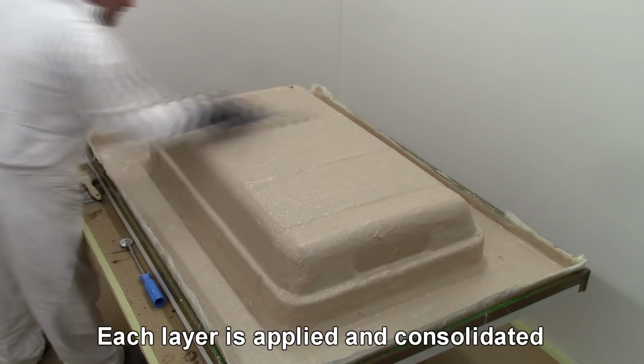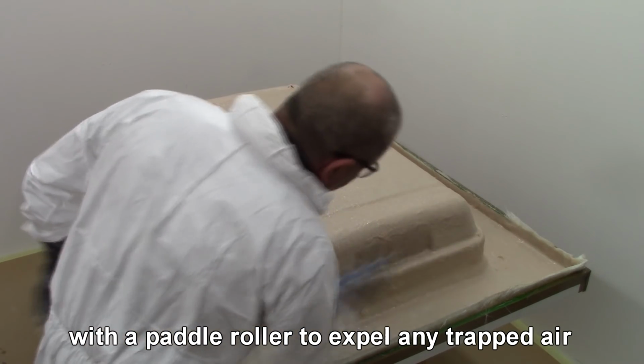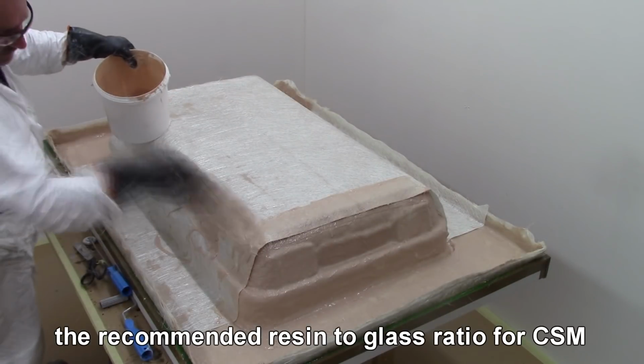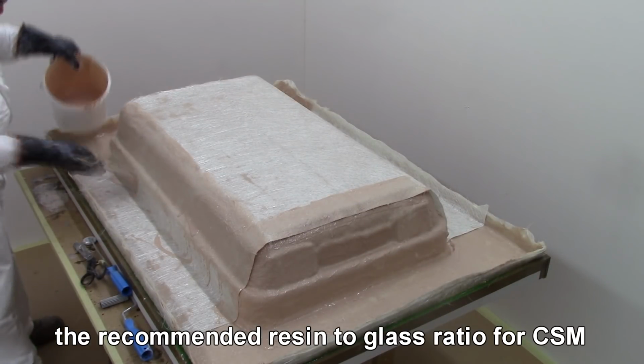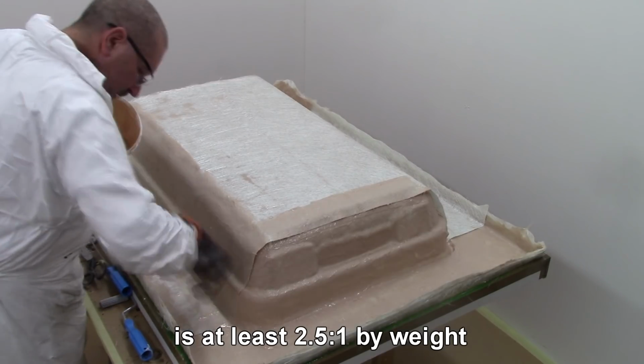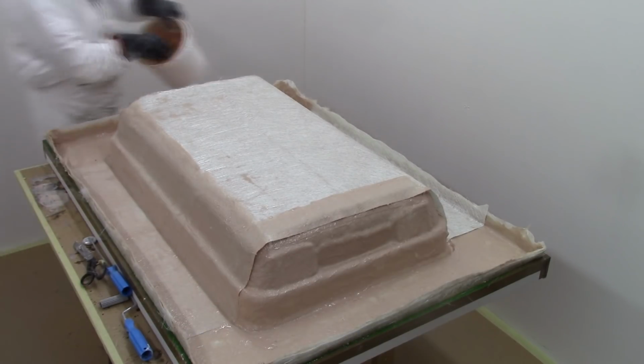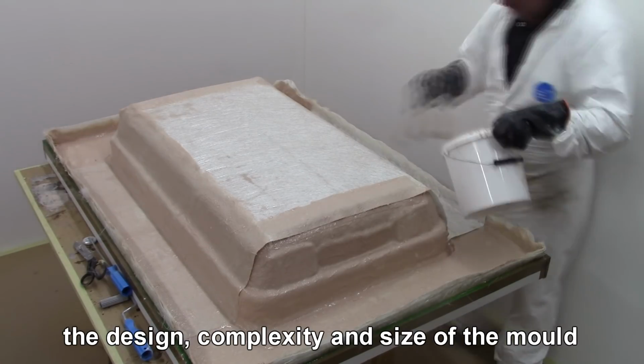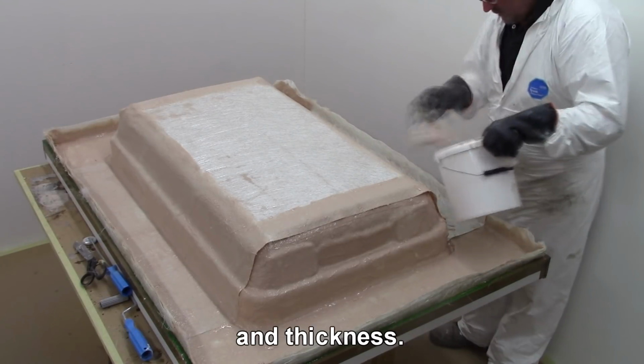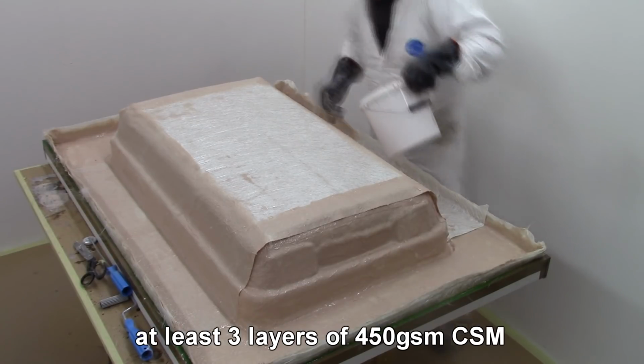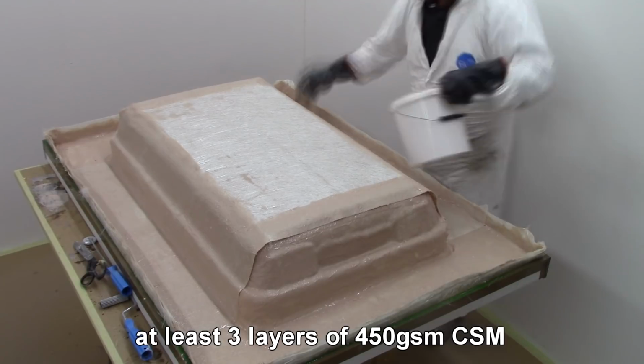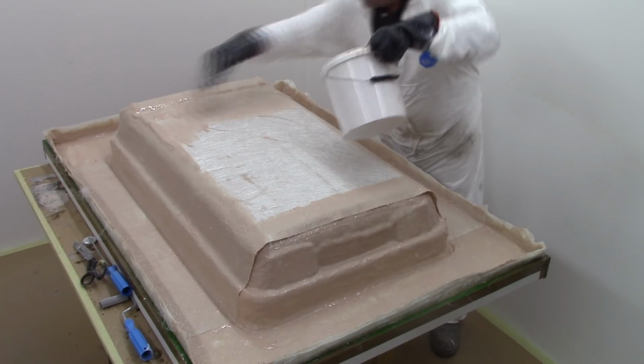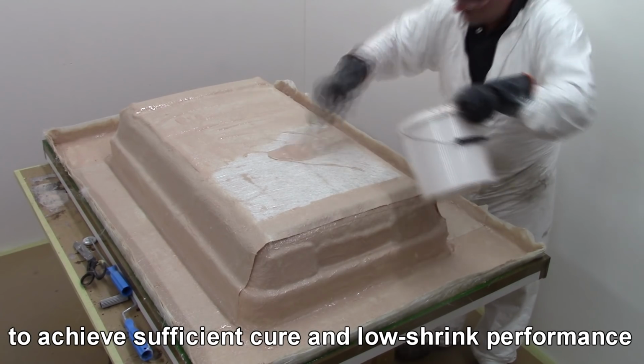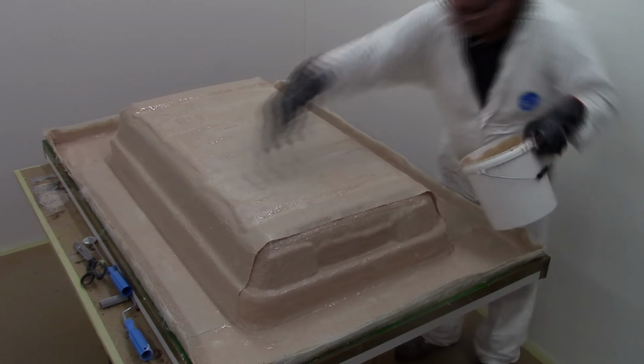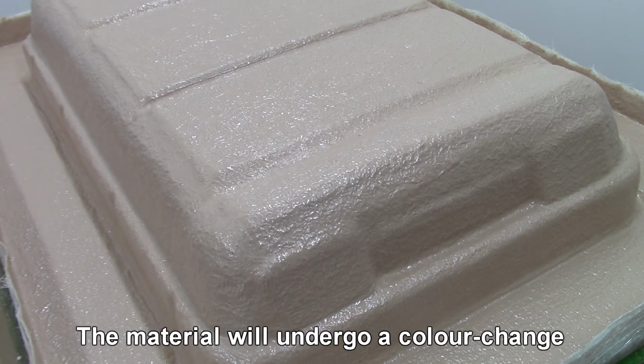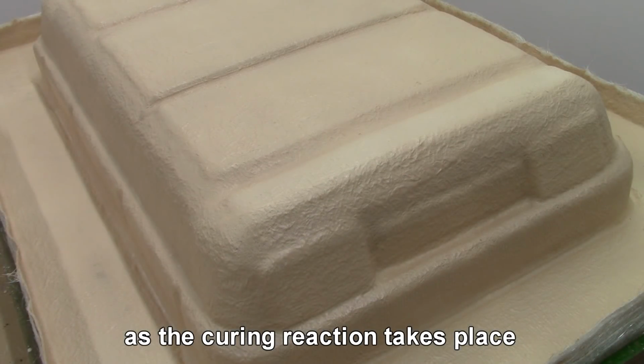Each layer is applied and consolidated with a paddle roller to expel any trapped air. The recommended resin to glass ratio for chopped strand mat glass reinforcement is at least 2.5 to 1 by weight. The design, complexity and size of the mould will determine optimum reinforcement levels and thickness. At least 3 layers of 450 GSM chopped strand glass mat or equivalent is required and should be applied in a single operation to achieve sufficient cure and low shrink performance. The material will undergo colour change as the curing reaction takes place.